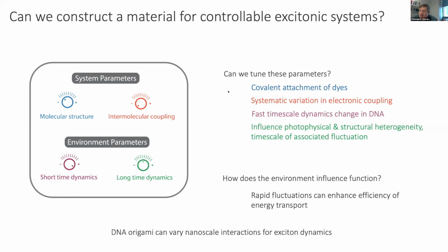Okay, so another question: what is the time scale of the angular fluctuations? Do you have any handle on how quickly those are changing? Yeah, so that is what was measured with the anisotropy, the angular fluctuations, which was in the DX tile 0.62 nanoseconds and in the duplex 0.12 nanoseconds. So it's somewhat comparable to the energy transfer rate, but essentially on other sides, so that we can kind of conceive of them in the static and dynamic limit.